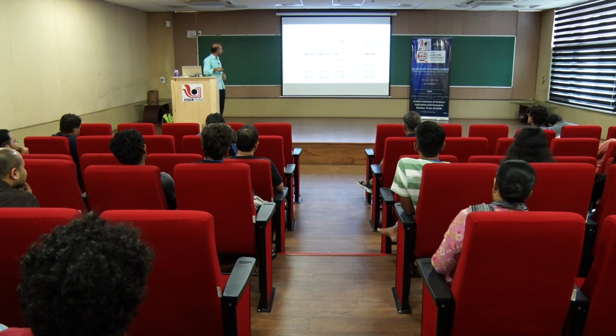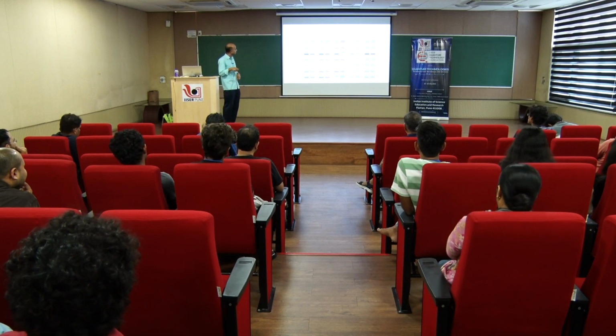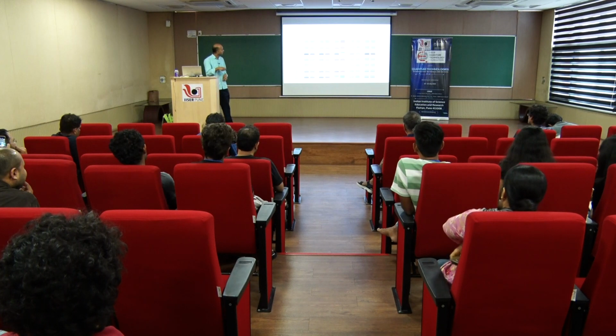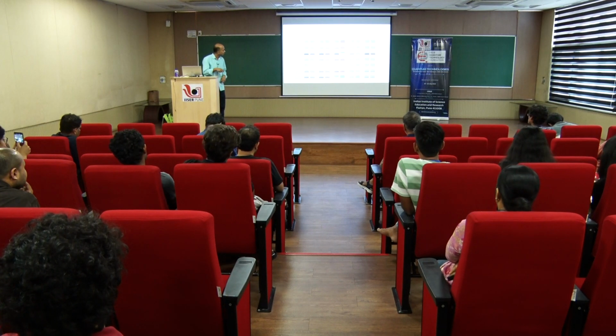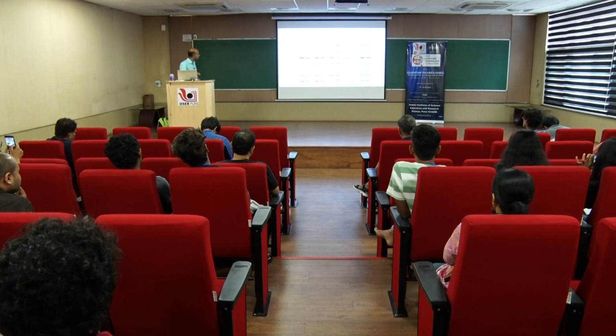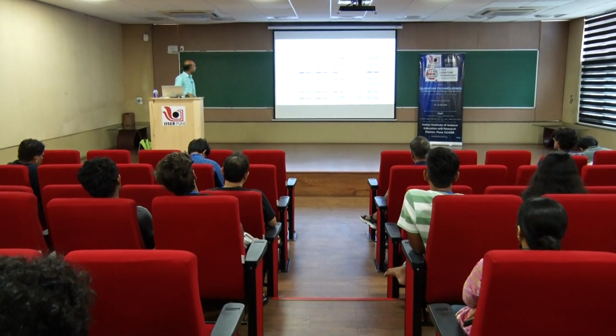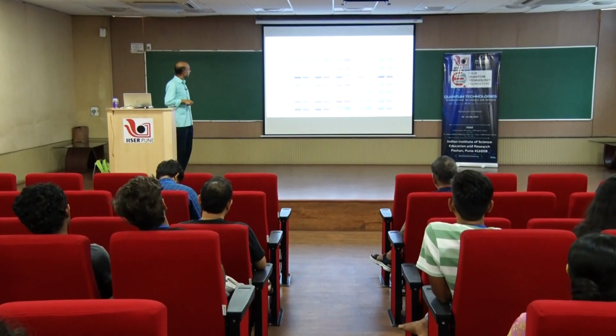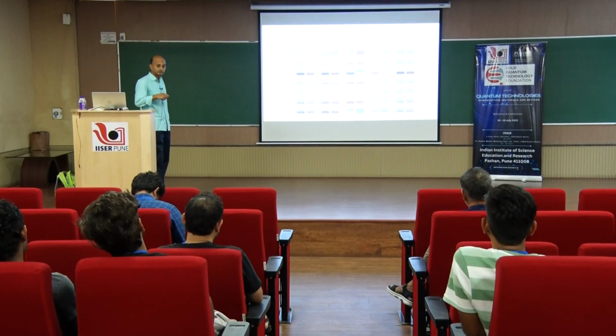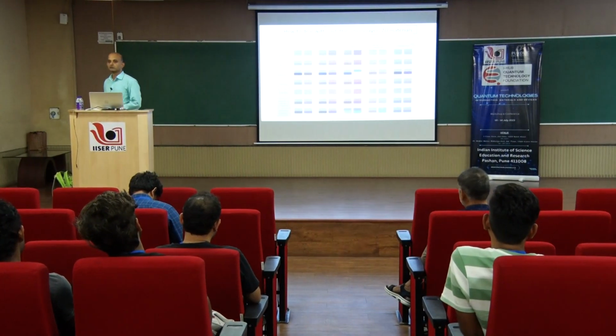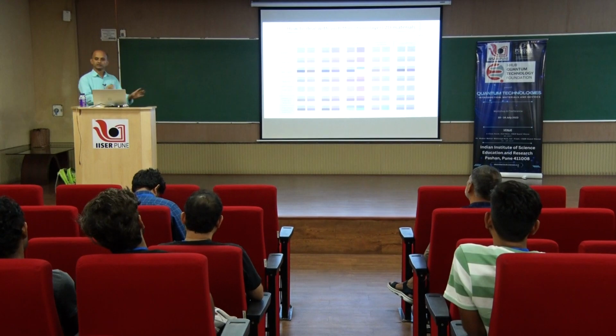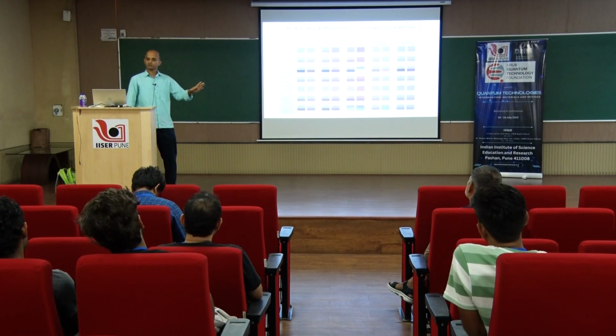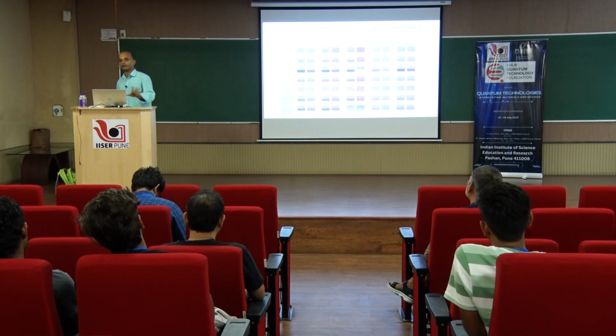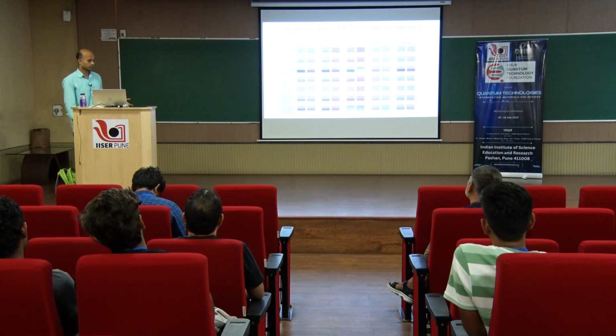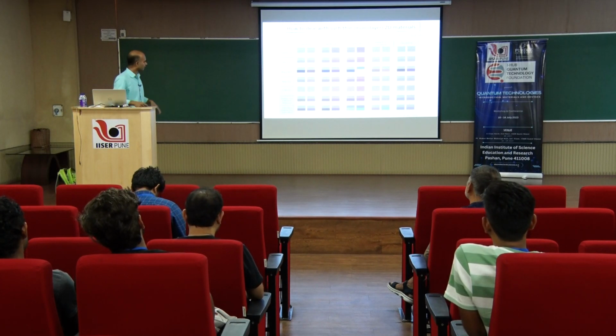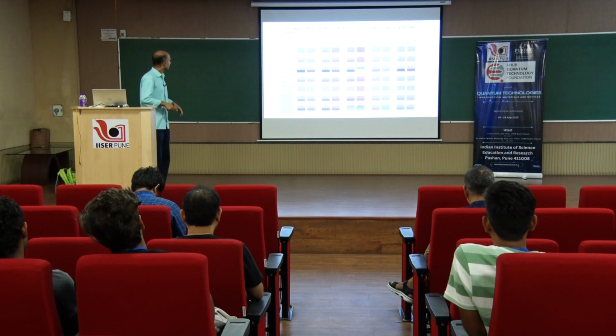Like here it is SiO2, here it is aluminum oxide, hafnium oxide, PMMA or PVA, and again it is aluminum oxide on top of aluminum. These are all on silicon, this is on aluminum. So, you can see that to see one layer graphene you need this kind of thickness, and if the monolayer is there you will be able to see it. So, you do not need any sophisticated instrument, just an ordinary microscope will tell you whether you got a monolayer or not. I mean, you have to train your eyes a little bit, but it is highly doable.